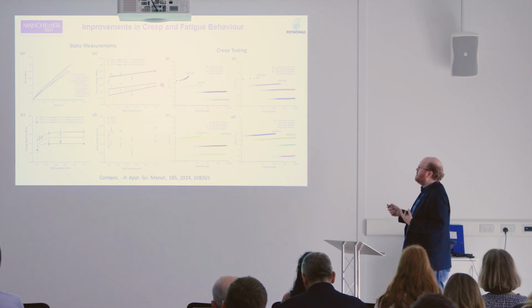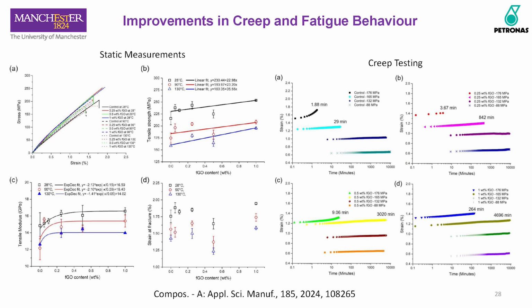This was very evident when we look at creep measurements. So this is creep at different temperatures and at different loadings. So the control here at very high loadings, we took 175 megapascals. It's failing after about 2 minutes. Adding just 0.25% of our material doubles that to almost 4 minutes. Going to 0.5%, now it lasts about 9 minutes. Adding 1%, now it lasts 264 minutes. So it's the same glass fiber composite. All you're adding is a very, very small amount of this material at the same load, and you're actually getting a massive improvement in its service life.